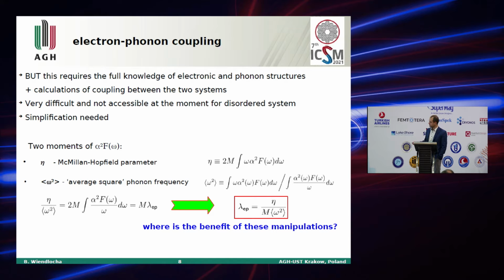And if you look at those definitions more closely, you can get the definition of lambda again by dividing the McMillan-Hopfield parameter by the mass times this average square phonon frequency. But what is the benefit of such manipulations? Because we didn't do any simplifications here, this is still an exact quantity.